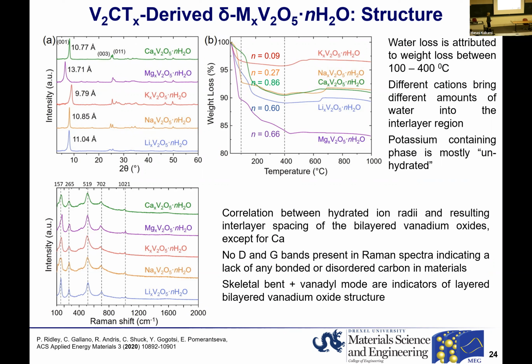Through the thermogravimetric analysis, we determined the hydration degree on all these phases, and we've learned that the magnesium pre-intercalated phase is the most hydrated, and the potassium pre-intercalated phase is the least hydrated, which again is in agreement with the water shell around these ions. But Raman spectroscopy showed us that there are no carbon bands in the Raman spectra, which essentially implied that all carbon that was originally in the chemical composition of the MXene phase precursor has disappeared. So carbon evolves from our system in the form of some volatile compounds, but we haven't analyzed what those compounds are.